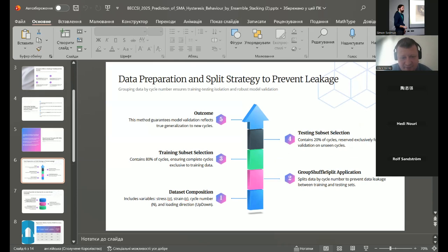The first was dataset composition. We move from bottom to top. It included variable stress, sigma, strain, epsilon, cycle number, n, and loading direction, up or down. So it's whether the curve is going up or down. Second one is group shuffle split application. It splits data by cycle number to prevent data leakage between training and testing sets.